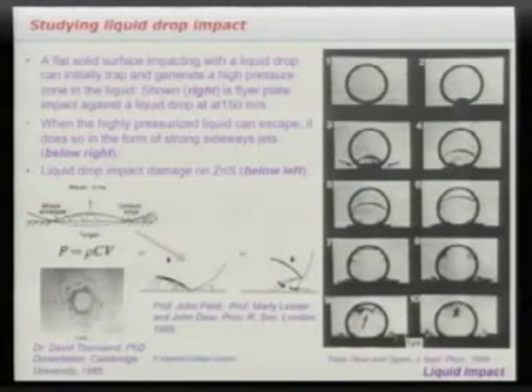The other area of research which we were interested in was the liquid drop impact problem, or rain erosion. And this shows the same technique where we had effectively a thin slice of liquid being impacted by a flyer plate, in this case at about 150 meters per second. Again, using a Schlieren technique, we could photograph the shock, and you can see here this region where you get very high pressures. The shock then passes up this free surface and generates outflow of liquid. And this jetting process is at remarkably high velocities. And then you get an interaction where the shock goes onto the rear face and then comes back and focuses again.